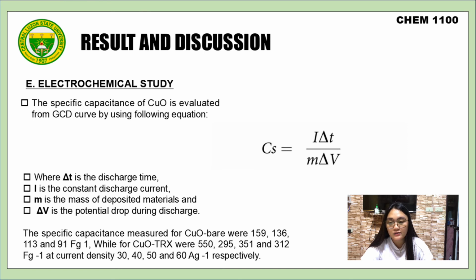The specific capacitance of copper oxide is evaluated from the GCD curve by using the following equation. Cs equals I ΔT over m ΔV, where ΔT is the discharge time, I is the constant discharge current, m is the mass of deposited material, and ΔV is the potential drop during discharge. The specific capacitance measured for copper oxide bare were 159, 136, 113, and 91 F/g, while copper oxide TRX were 550, 295, 351, and 312 F/g at current densities of 30, 40, 50, and 60 A/g.